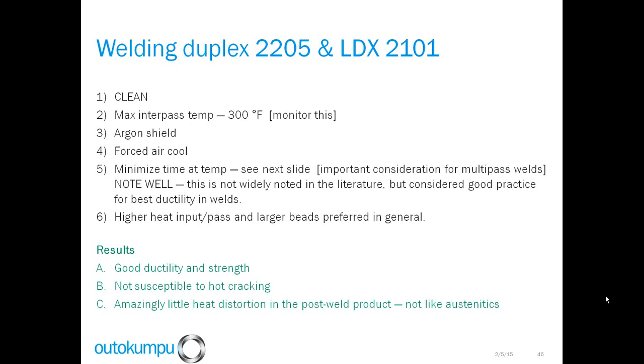We found, contrary a little bit to what Gary was saying earlier, we use a high heat input per pass, and the large beads worked well for these rounds. I think it's probably a bit of a personal preference thing. That's what our shop likes to do, and we found it worked fine in this application. And the results, and we did a bunch of testing for the client, are great ductility, great strength. There's little or no hot cracking. I don't think I've ever seen either of these alloys hot crack. And the lack of distortion is a huge bonus. When we work with the austenitics, we have plenty of distortion problems, and this material behaves much more like a straight-up carbon when we weld it.